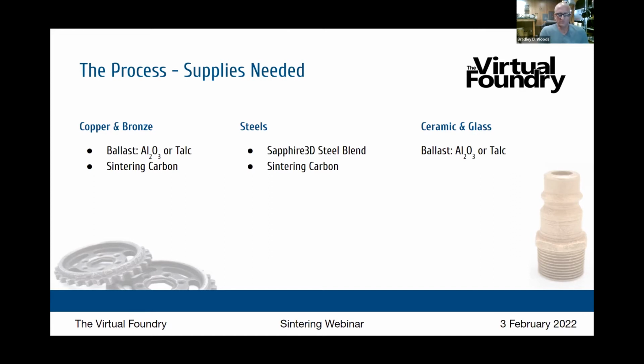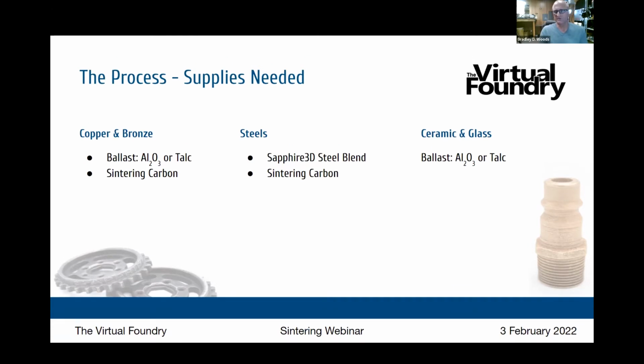After that, we now recommend that people do the sintering in a two-step process. So they'll set up, bury the part in Al2O3, and debind it. As a secondary process, they'll take the brown part out of the Al2O3 ballast, and it's still strong enough to handle. It's a brown part. It would break if you dropped it, but it's plenty strong enough to handle, and you can actually manipulate it if you want or sand it.